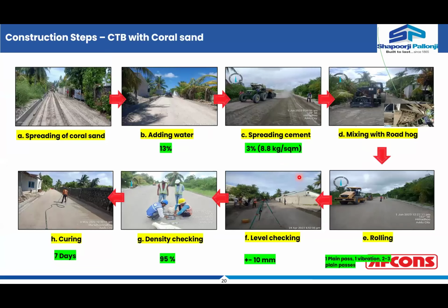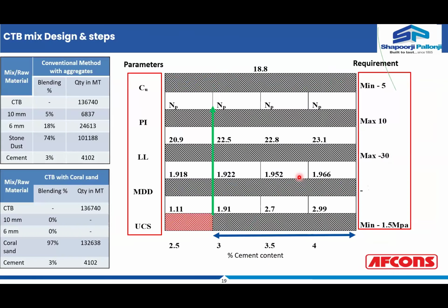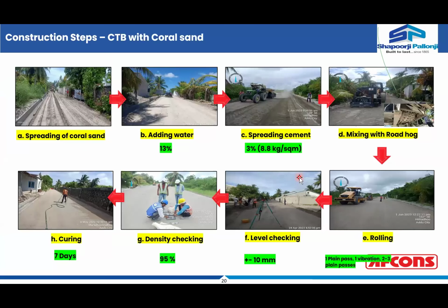Now, when it comes to the field, instead of 4 proportions to be blended together, you have only 2 proportions to be blended, that is coral sand and cement. Instead of 10, 6, stone dust and cement blending, you can blend the coral sand and the cement. So the processing time has reduced a lot as far as the mix is concerned. So spreading of coral sand, adding water to the coral sand, and doing the mixing, the harrowing using the grader, and then spreading the cement required, either manually or with RM300.